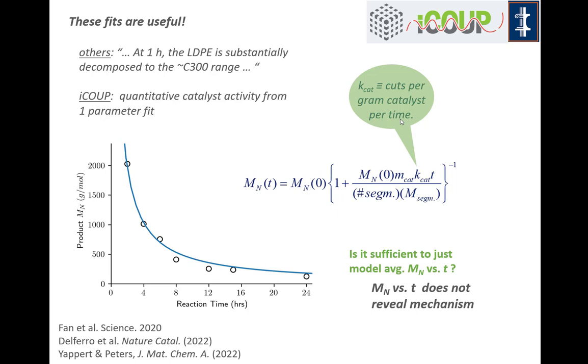This also points out something important: going back to the original question, is it sufficient to understand mechanisms by just monitoring the average molecular weight versus time? If it's universal and we haven't said anything about the mechanism to derive this equation, then that's a universal feature that does not reveal anything about the mechanism. In a couple of places in the literature you'll see claims that average molecular weight evolution is consistent with a certain mechanism — but it's consistent with all kinds of mechanisms.